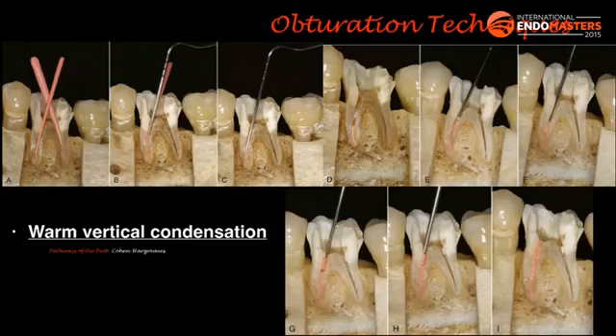After the adaptation of the master cone, it is removed and sealer is applied. The cone is placed in the canal and the coronal portion is removed with heat. A heated spreader or plugger is used to remove portions of the coronal gutta-percha and soften the remaining material inside of the canal. Touch and heat is an alternative to applying heat with a flame-heated instrument because it permits temperature control. A plugger is inserted into the canal and the gutta-percha is compacted, forcing the plasticized material apically. The process is repeated until the apical portion of the canal has been filled. The coronal space can be backfilled using small pieces of gutta-percha.